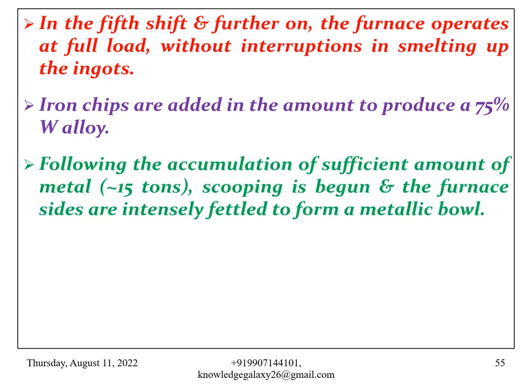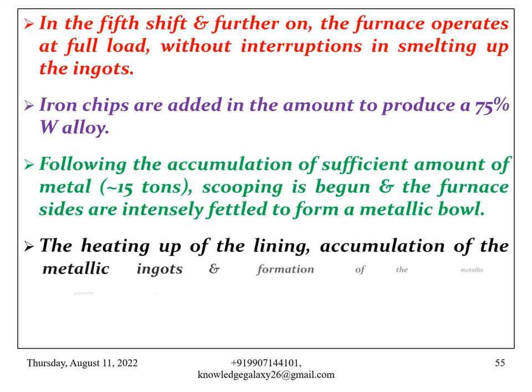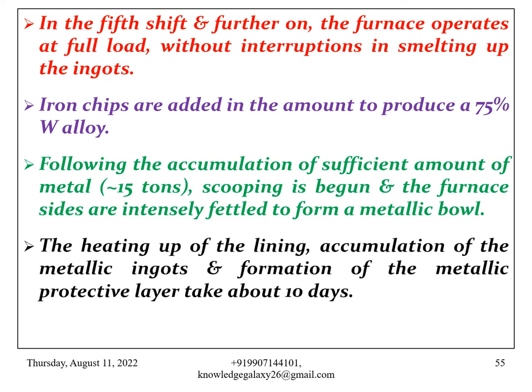Following the accumulation of a sufficient amount of metal, approximately 15 tons, scooping is begun and the furnace sides are intensely fettled to form a metallic bowl. The heating up of the lining, accumulation of the metallic ingots and formation of the metallic protective layer takes about 10 days.